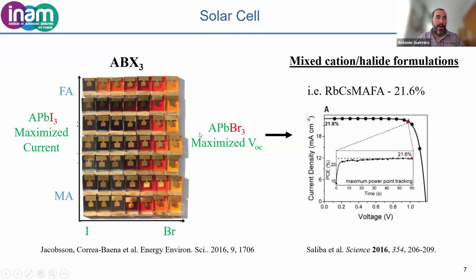Depending on the electronic properties and the bandgap of the material that is synthesized, we could maximize the current output that can be obtained from the device, and this is usually obtained for materials containing iodide because the bandgap is narrow, or we can maximize the open circuit potential that can be obtained in the device when we work with bromide.